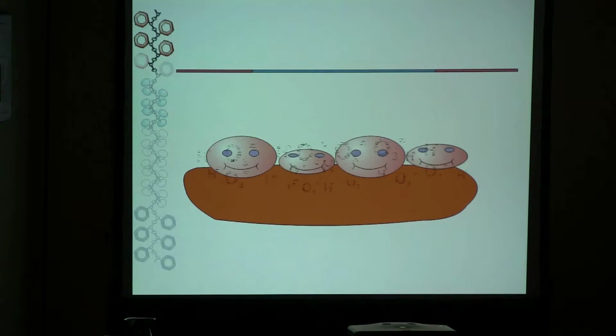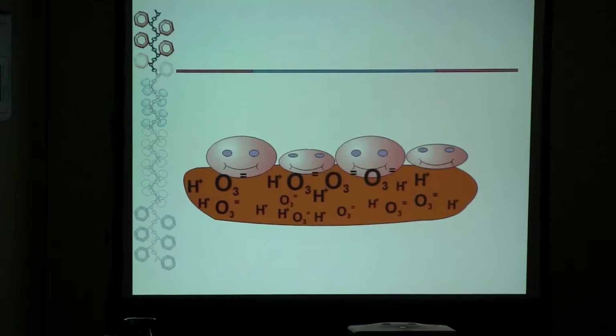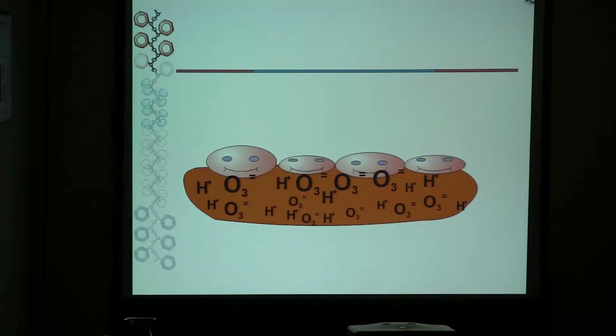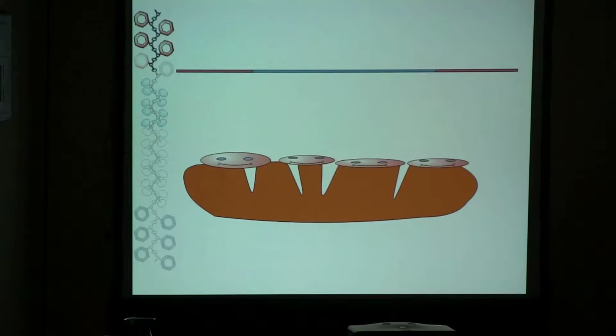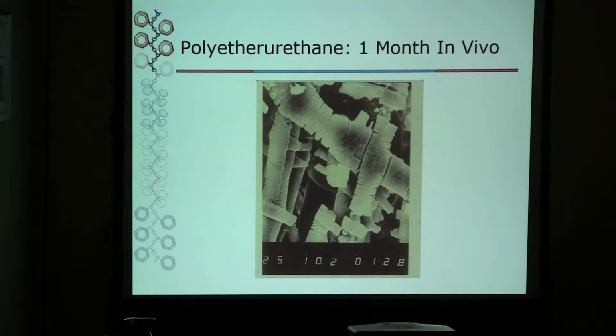Your granulocytes, or macrophages, leukocytes, etc. They come to your polyurethane material, which is in motion, and they secrete superoxide and hydrogen ion, and the pH can go down as low as 1. And small molecules get cleaved off as the material begins to flex, and as it flexes and embrittles, it begins to crack. And we're left with this cracked substance that I showed you a little bit earlier.